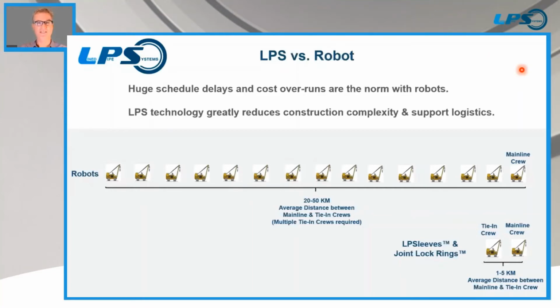And because the robot can't coat as fast as people can weld, the robot crews end up getting far behind the mainline crew. From the projects that we've heard from, primarily in Chile, but I'm sure it happens elsewhere, if the mainline crew is moving along at a fast pace, the tie-in crews and the robot crews will be left far behind, 20, 30, 40 kilometers we've heard, and often extend project timelines up to at least a few months, which just costs tens of millions of dollars. So the all-in cost of supporting those robot crews spread over tens of kilometers is far, far greater than just the actual cost of the robot coating itself. You have to have support crews, and it really increases complexity for the entire construction project and logistics. You can't completely bury all the pipe until the robots are done. So that's one of the primary reasons several large contractors really refuse to use the robot.